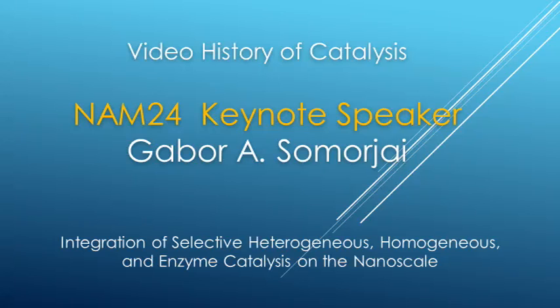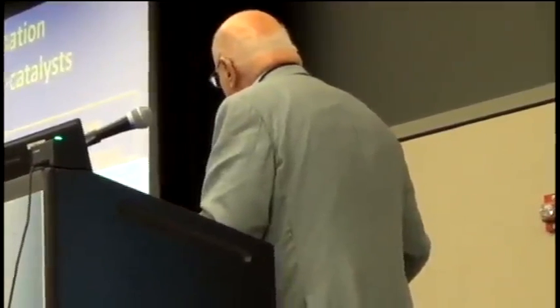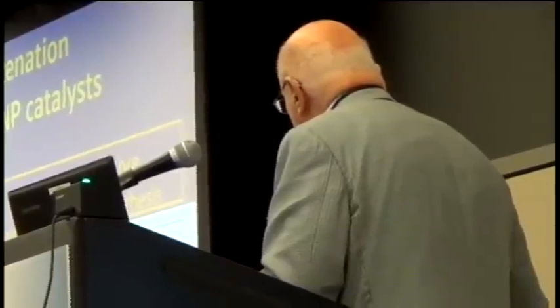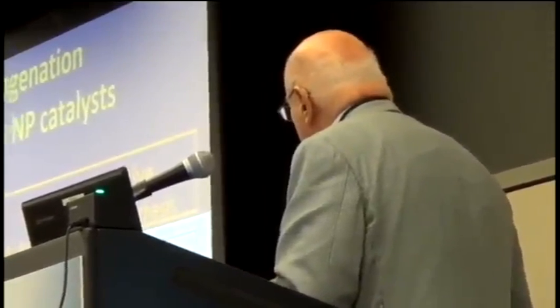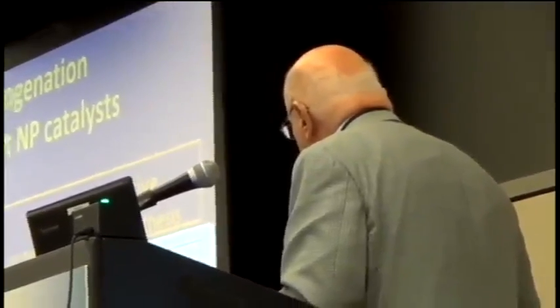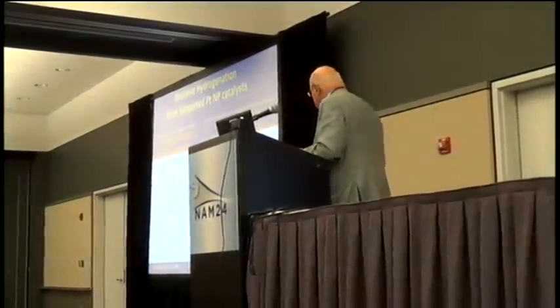There was a good study with the Boudart group at Stanford showing very broad distribution of particles from incipient wetness, oxidation reduction, and it concluded that most catalytic reactions are not structure sensitive. It doesn't matter what the particle size in this distribution is, except maybe ammonia synthesis. That was very visibly structure sensitive.